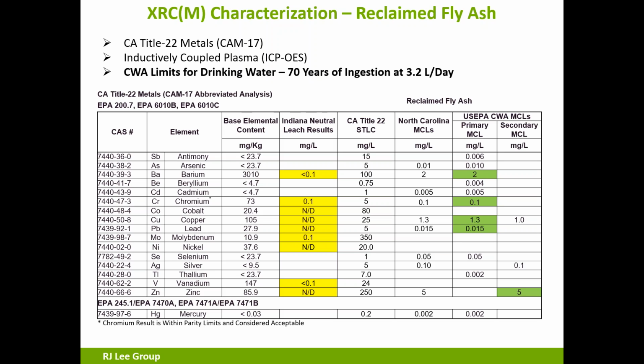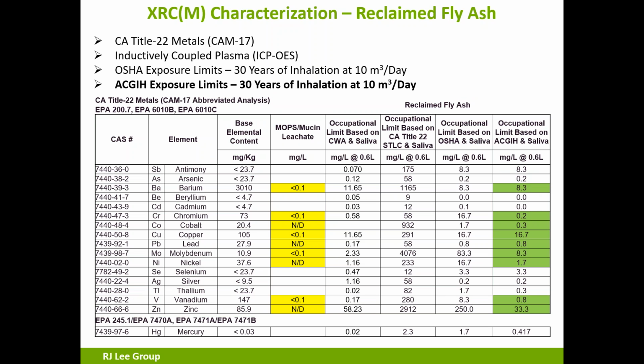For the environmental, we run it through our Indiana neutral leach, and we find out that for all of the metals that were actually detectable in the raw material, we've gone to not analyzing for all 17 metals, only those that show detection, above detection in the raw material, in the as-presented material. All of them passed our most stringent criteria, US EPA Clean Water Act MCLs. So it does not leach metals. For occupational, once again, we run it through our BioLeach process and compare it to ACGIH inhalation levels, convert it over to saliva ingestion, and we find out that it has cleared all of those hurdles as well.